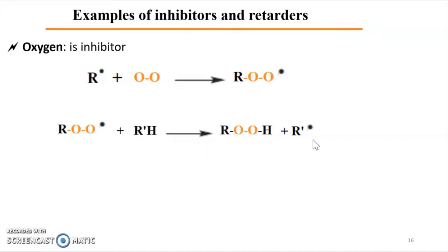which will be able to restart or not the polymerization according to its reactivity to the monomer present in the medium. So here the presence of oxygen influences not just the starting of the polymerization by delaying it, but also the efficiency of the initiator, because we have consumption of part of the initiator in the medium and also creation of initiators. So the real quantity of initiators in the medium during the polymerization process will not be well controlled or well known. So that's why during processing we have to make degassing under nitrogen to remove all oxygen from the polymerization medium.